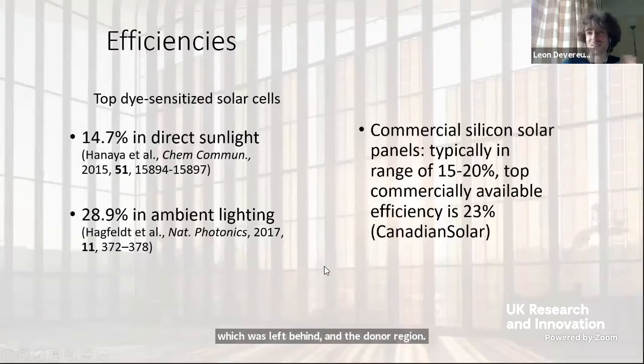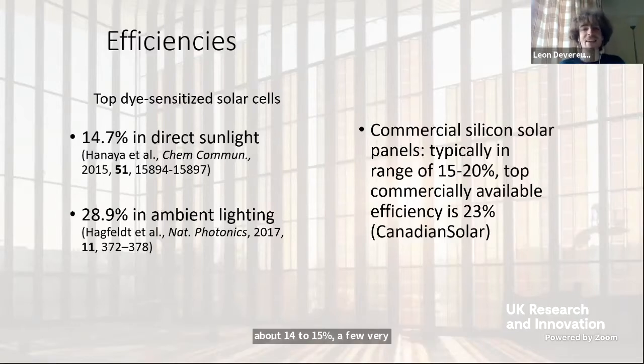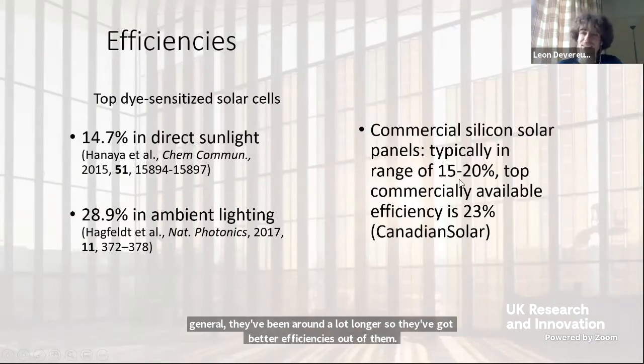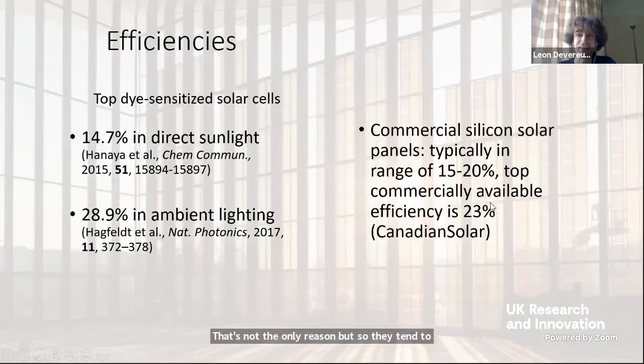So talking a little bit about efficiencies quickly, the top dye-sensitized solar cells are generally about 14 to 15% if you're very lucky. And the regular silicon solar cells, a bit higher in general. They've been around a lot longer, so we've got better efficiencies out of them. That's not the only reason, but so they tend to be 15 to 20%. The highest commercially available is about 23%, which is pretty good. There are other specialized ones which you can get much higher, but these are kind of the widely available ones we see.